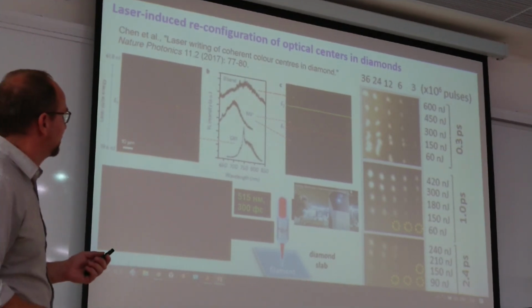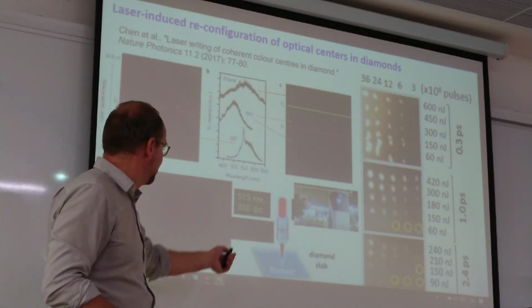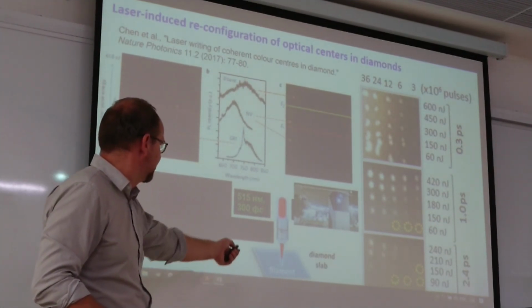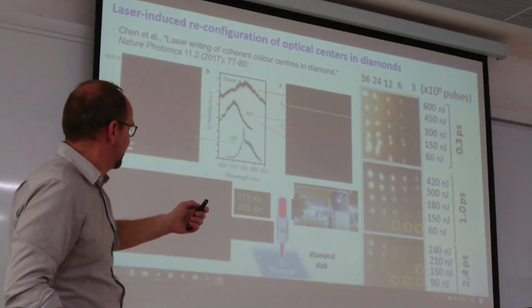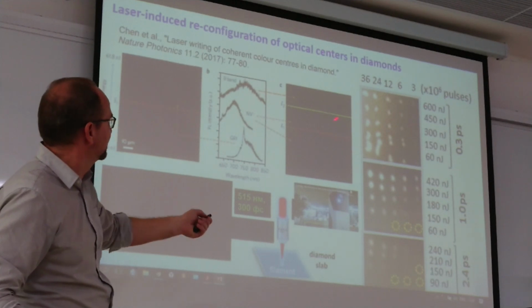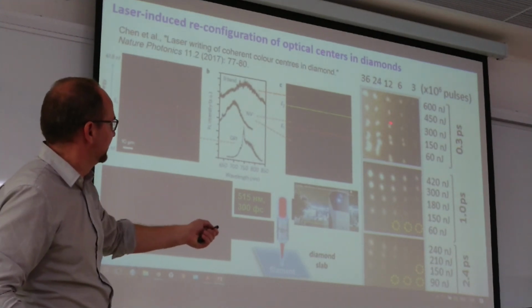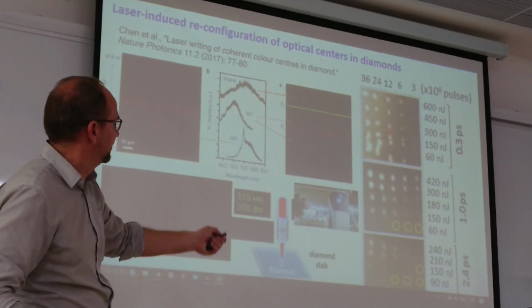Now we can come to the atomistic transformation. The technology looks very simple. We just focus the laser inside the diamond slab, and we are producing separate dots inside the diamonds at different pulse energies and different exposures. So these are using different pulse widths.